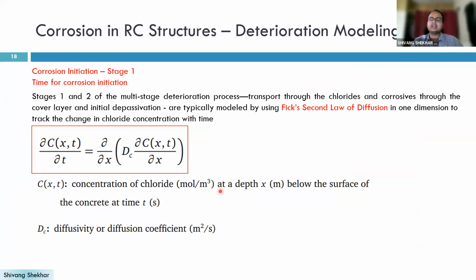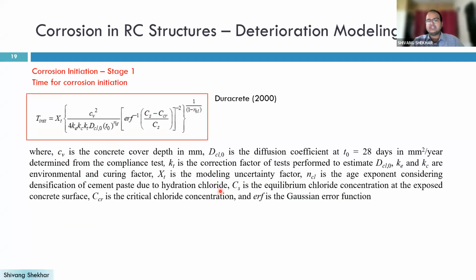They develop a mathematical model for finding the initiation time of corrosion, and basically this depends on Fick's second law of diffusion. When we solve this differential equation by applying boundary conditions, there are several literatures available that give, based on several parameters, what the initiation time will be. If you see this equation, it is very much used in the literature to assess the corrosion initiation time